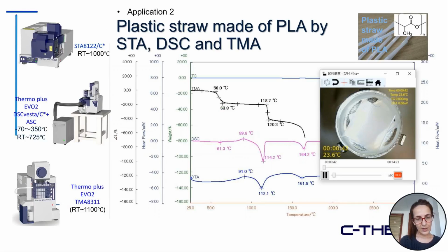Again, we put all this data in the same graph in order to have a better idea about the thermal analysis of these plastic straws. As you can see, in the TMA analysis we have three shrinkage steps, but we don't see the cold crystallization temperature in the TMA. This is only observed in the DSC experiments, followed by two endothermic peaks, which again are related to some transition in the PLA, and finally melting at 164. In the detailed analysis, we couldn't observe the glass transition temperature. However, we can see the cold crystallization temperature and also the melting temperature.